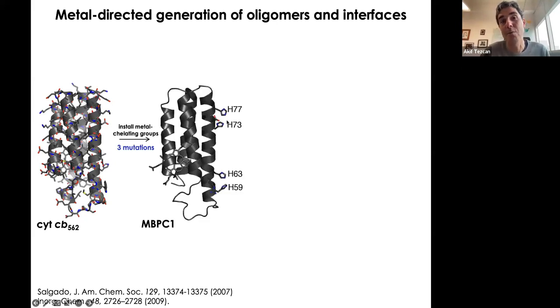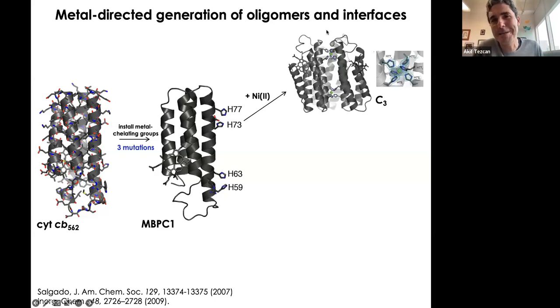So what we then did was to place histidine residues that are one helix turn apart to give us these bidentate chelation modes that we thought would nucleate metal ions more selectively than if we just had monodentate ligands here. And we made this building block with 2 pairs of histidines. And what we saw was that when we added nickel(II) to this, we got a C3 symmetric trimeric assembly. So 1, 2, 3, this is a crystal structure, and that's dictated by the nickel coordination. It turns out nickel(II) likes octahedral geometry, so it likes 3 pairs of histidines around it to get a trimeric structure.